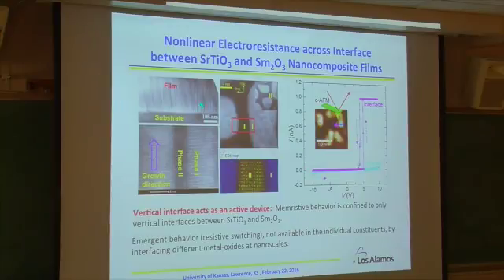So basically, if you look at this cross-sectional TEM, the plan view, the phase 1, phase 2 material, or magnify this, then we just use the conductive AFM scan across the interface. It's very, very interesting. Sorry, the colors really didn't show very well. If you look at the column or matrix, at this given field, it's almost flat. However, right across the interface, you have a huge conductivity.